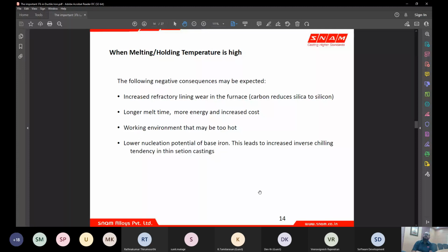So longer melting time means more energy consumption and increased cost. And the working environment can be very hot, so it will become very difficult for the operators to handle, and handling a ladle starts becoming weak. And as we know, it can lead to lower nucleation potential. That means it can lead to thin section carbides, or demand for more nuclei, or all nuclei-deficiency related defects in the castings. Low nodule count, increase in chilling tendency, increased hot spots, remote location microporosities or micro shrinkages can come.